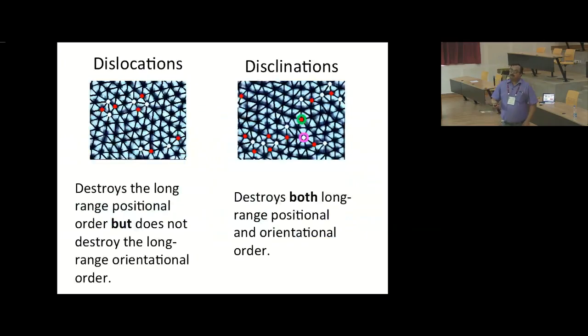All right, now let's look at it a little more carefully. We have two kinds of defects that set in at different characteristic fields. One is dislocations, and the second is disclinations, which are these isolated 5-fold and 7-fold defects. And what I told you is that dislocations destroy the long-range positional order but do not destroy the long-range orientational order. In the case of disclinations, they destroy both.